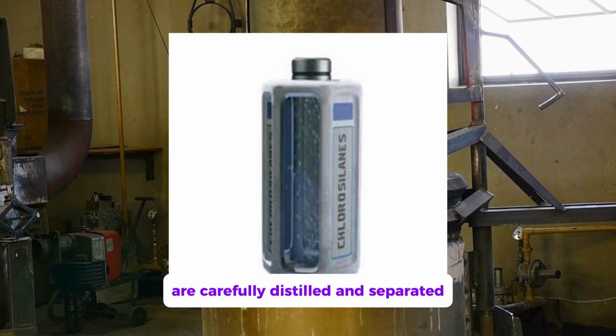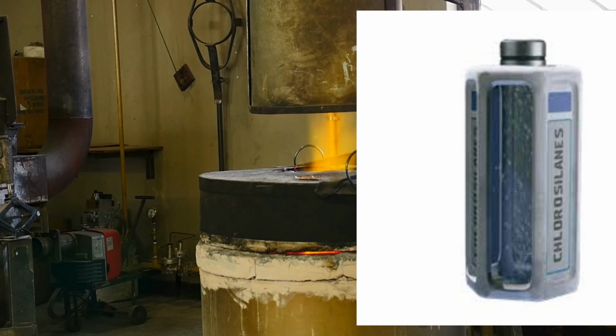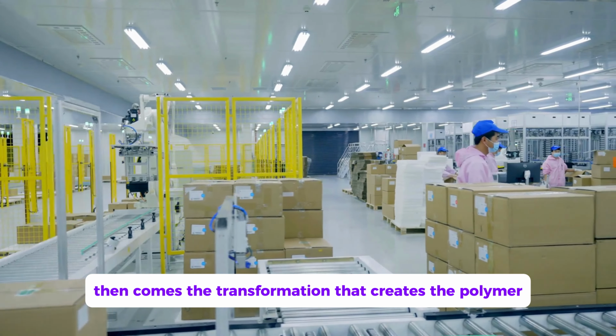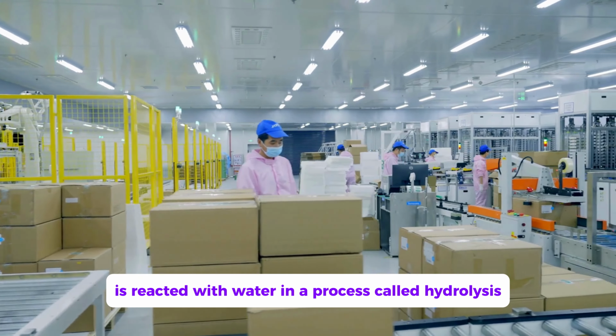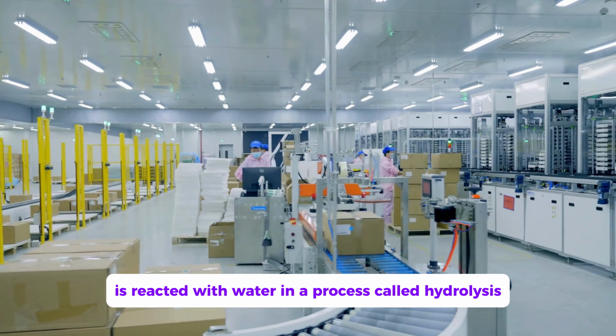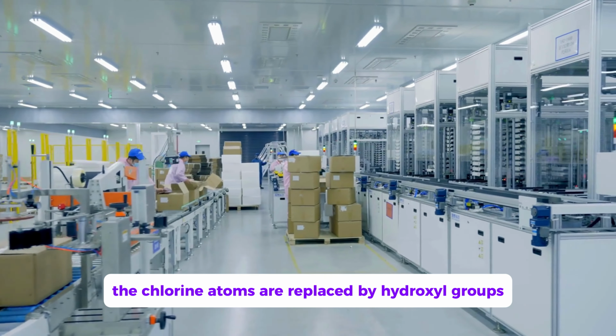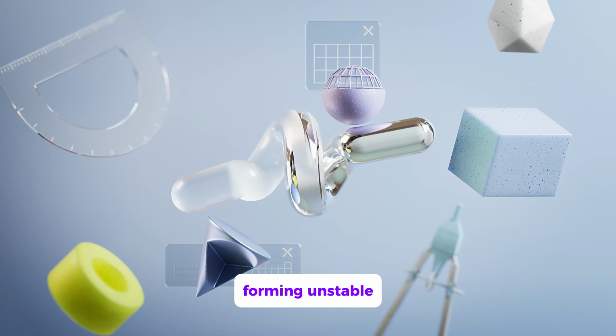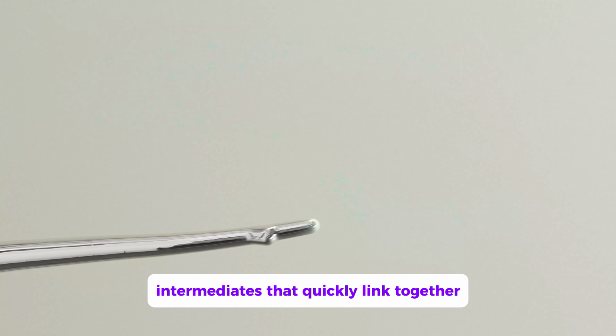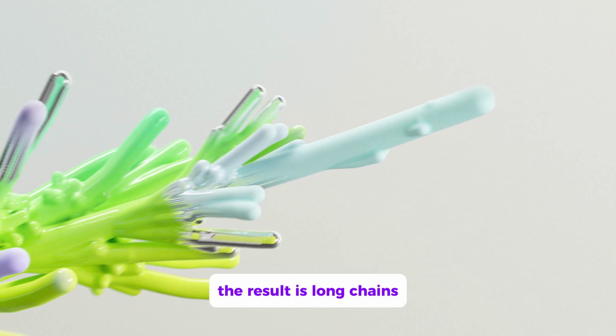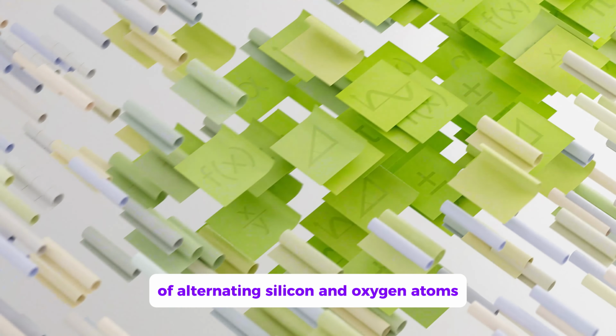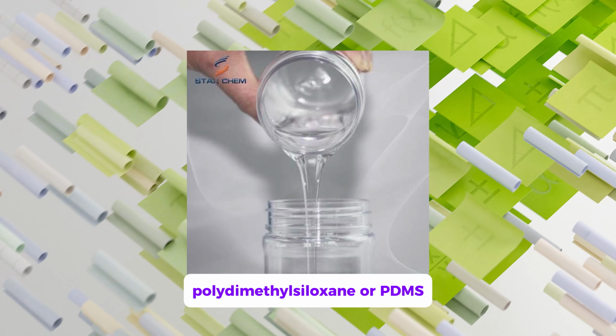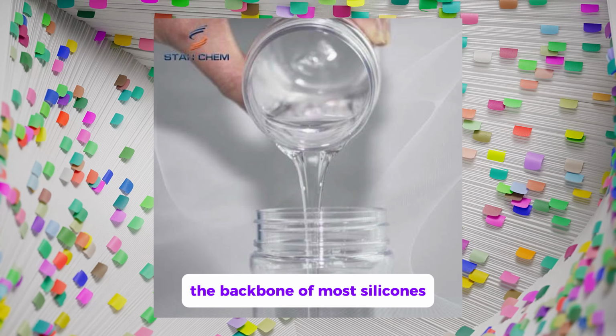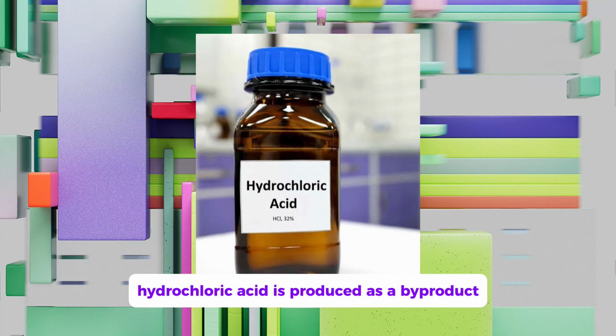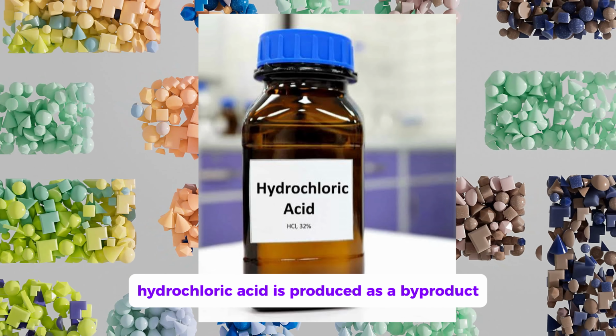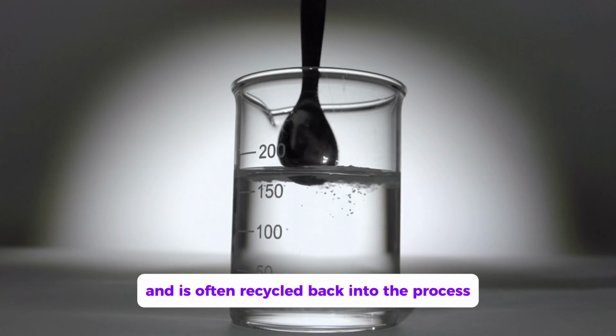These chlorosilanes are carefully distilled and separated. Then comes the transformation that creates the polymer. Dimethyldichlorosilane is reacted with water in a process called hydrolysis. The chlorine atoms are replaced by hydroxyl groups, forming unstable intermediates that quickly link together. The result is long chains of alternating silicon and oxygen atoms, polydimethylsiloxane or PDMS, the backbone of most silicones. Hydrochloric acid is produced as a byproduct and is often recycled back into the process.